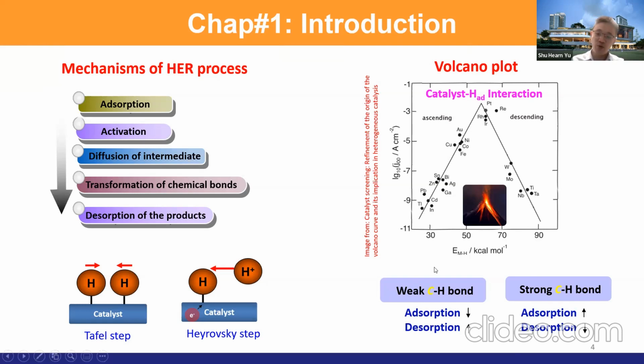On the other hand, we can have a weak catalyst-hydrogen bond interaction. Because of the weak interaction, the adsorption step is rather slow. However, the desorption step of the molecular hydrogen is fast. Overall, the reaction will be slowed down as well. So we need to find a catalyst that has an optimal interaction rather than a strong interaction. So that would be platinum, which can be visualized by the volcano plot.